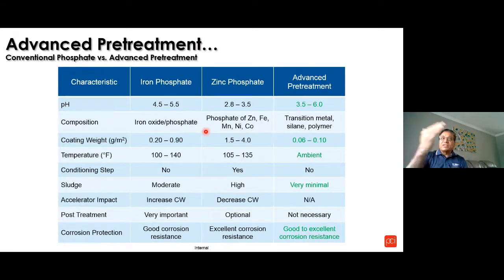Again, conventional versus the advanced pretreatment. I won't go into the details. You guys can see on the slide. Significant difference in the coating weights, and that's why there's less sludge. The key focus is ambient temperature, sludge very minimal, and performance equal or better. Equal or better from the hundreds of lines that are running using the zirconium pretreatment in the marketplace. Less number of stages, as I mentioned.